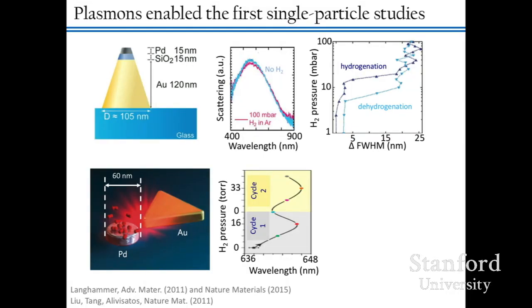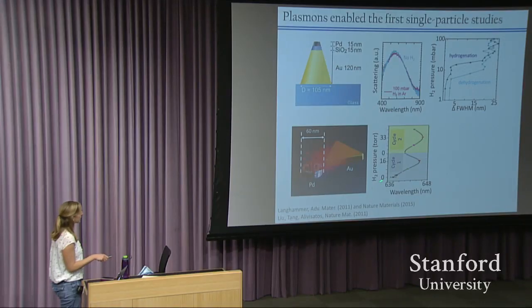There was a related study by the Alivisatos group that was published shortly thereafter, where they had the planar version of this structure. Again, there's a gold nano antenna. I should mention that these gold nano antennas support surface plasmon resonances that basically allow light to be focused onto the palladium nanoparticle and then allow the phase to be transduced as an optical signal into the far field. So in this planar analog, they mapped out something like an isotherm, so hydrogen pressure versus wavelength.